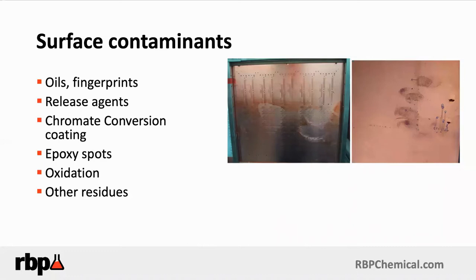Here is oxidation, because again, either from poor rinsing or rinsing with too hot water, let the board sit. Keep in mind, rinse tanks are not holding tanks. You should be rinsing for the proper amount of time with good, clean, deionized water, and then get the panels through the process and not wait to go to the next step. And if it oxidizes, that means you're not drying the panels properly, or you're using poor quality water. And this is potentially going to cause issues with resist lock-in, where you're going to get residues left on the surface and situations like that.